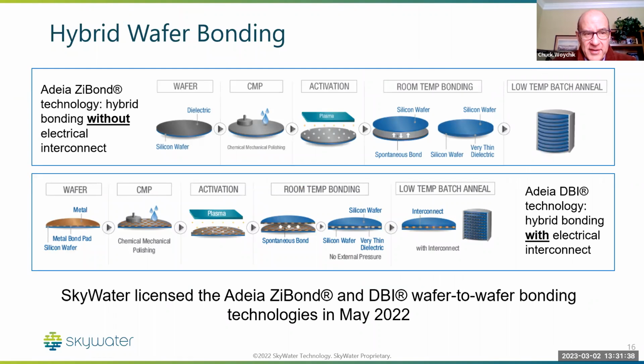Another platform for SkyWater is really the hybrid bonding. So SkyWater has licensed the Adeia oxide bond. Their trade name is called ZiBond, and also the hybrid bond, their trade name is DBI. So right now we offer both these platforms at SkyWater, again on a 200 millimeter platform. We've shown success for both of these. Currently we are using a SUSS XPS 200 tool, which is ideally suited to do really high volume manufacturing for these two processes. The important thing right now with the hybrid bonding, we've shown that for a silicon-silicon wafer, we can achieve 100% bonding with a 4 micron pad, 8 micron pitch with the Adeia technology that we licensed.